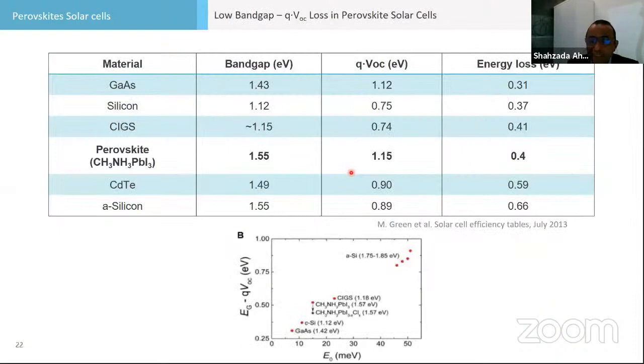Why has perovskite attracted so much attention? Because if you look at the best semiconductor, it's gallium arsenide, the III-V junction based solar cells. With a band gap of 1.43, you can get a VOC of 1.1, so the losses are less. Silicon's losses are also less, a little bit higher. Perovskite has similar losses to silicon because the defect tolerance is very, very high. If you take methyl ammonium lead triiodide, the band gap is 1.55 to 1.57, and we can harvest at least 1.15 volt. So the losses, like radiative recombination, are less.